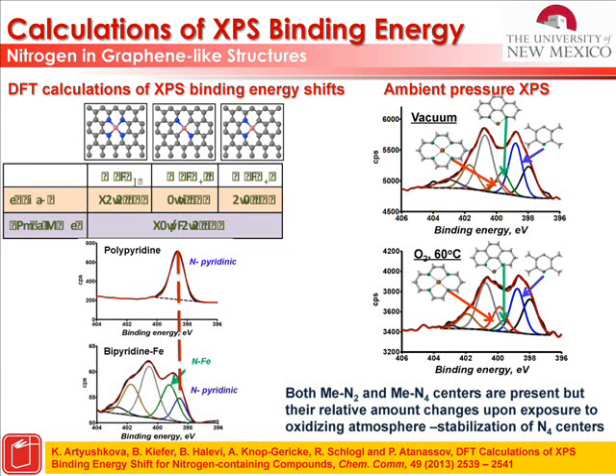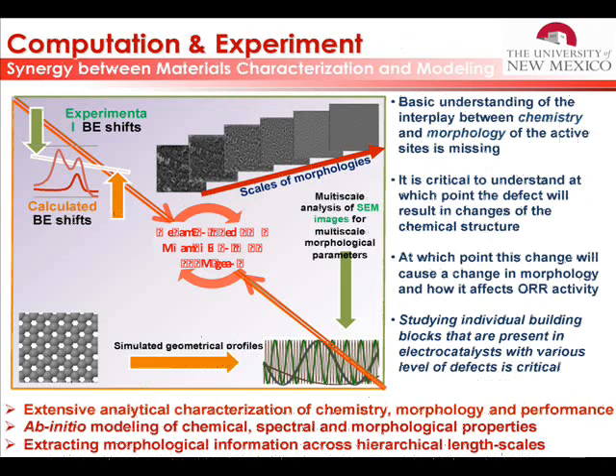And here is a demonstration of the iron in an N4 site. This is a first observation, direct observation. This is not a calculation. So the beauty of the high resolution TEM is that you can fantasize through TEM and then through DFT, and then you can see something and say, okay, whatever I did in DFT is good, because you can actually do in DFT almost anything.